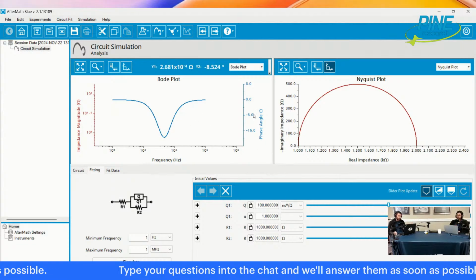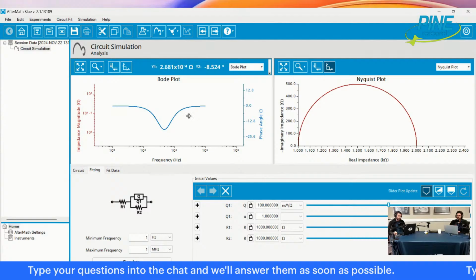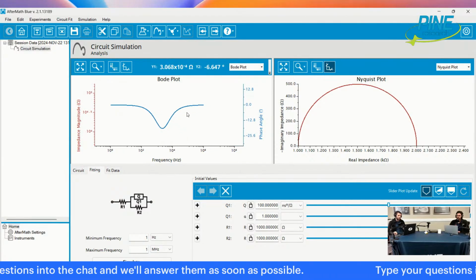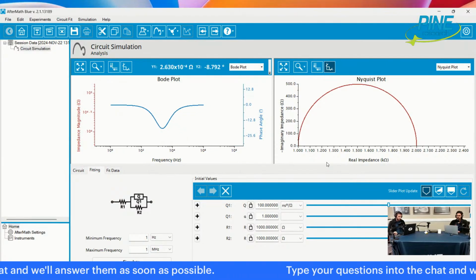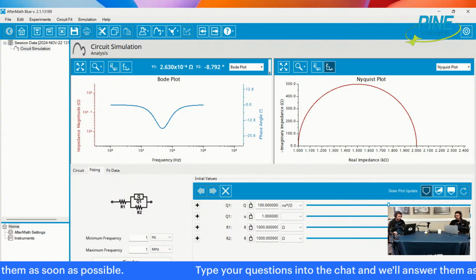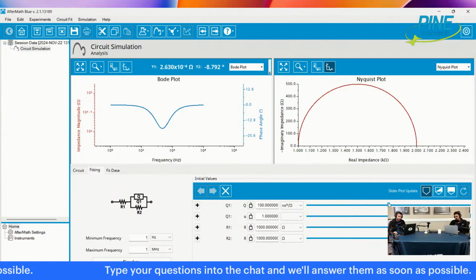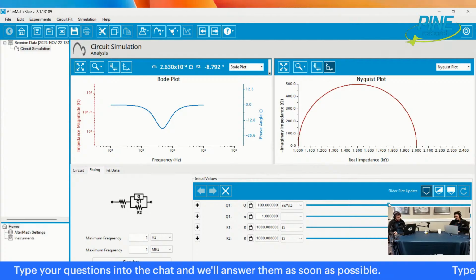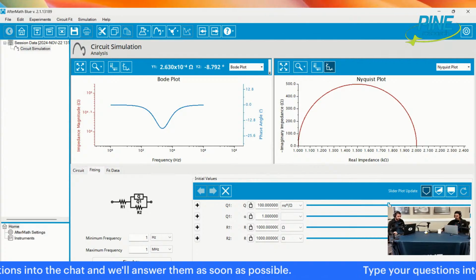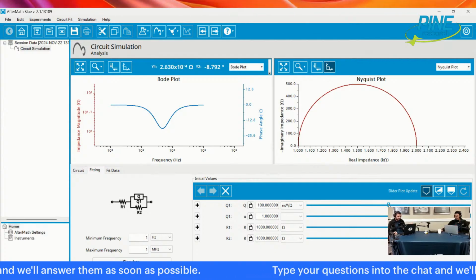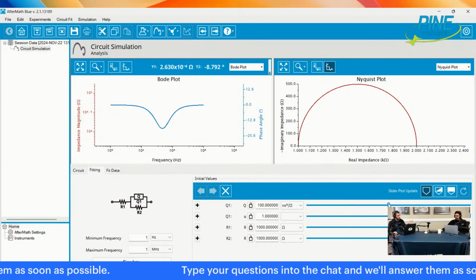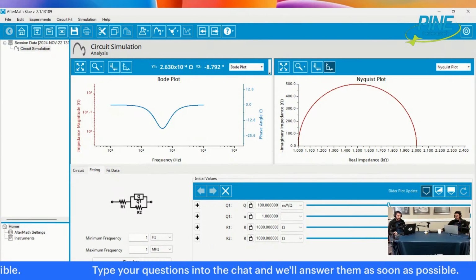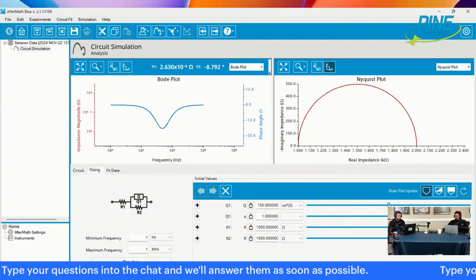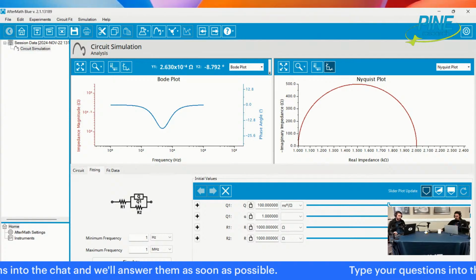Okay. You don't always see, for example, a peak in the phase angle at open circuit, but it does mean most probably that there is an interface, not necessarily a charge transfer process, although possibly a charge transfer process in some regard. It's just typically you have to polarize towards whatever you're doing. Let's just say, okay. So let's just look at practically what happens if the peak shifts to higher frequency.